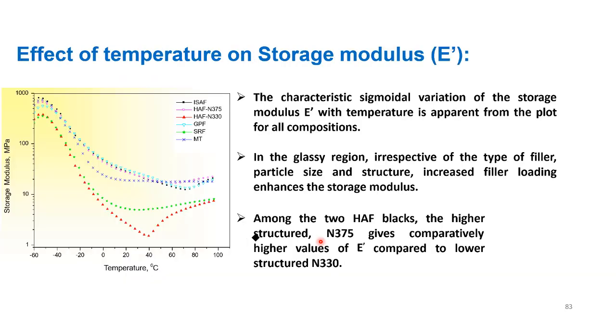The same effect on the storage modulus is also seen. The characteristic sigmoidal variation of the storage modulus with temperature is apparent in all the compositions, as you can see. Then in the glassy region, irrespective of the type of filler, particle size and structure, increased filler loading enhances the storage modulus. So here the size does not vary the behavior of the material for the storage modulus property. But we can see for the smaller particles, with increasing filler loading, the storage modulus is increasing.